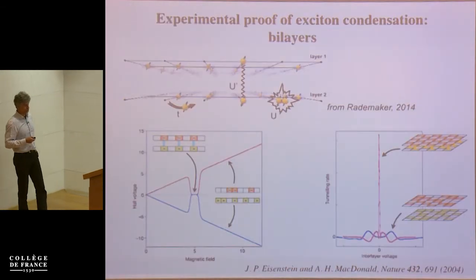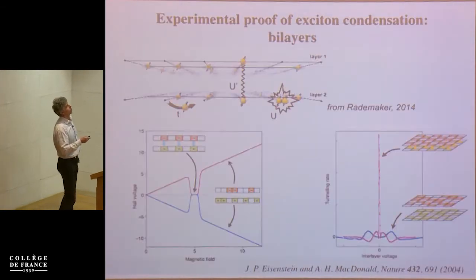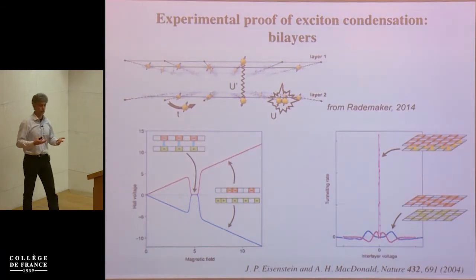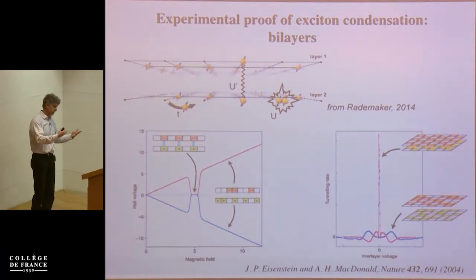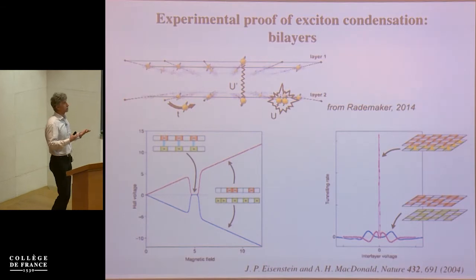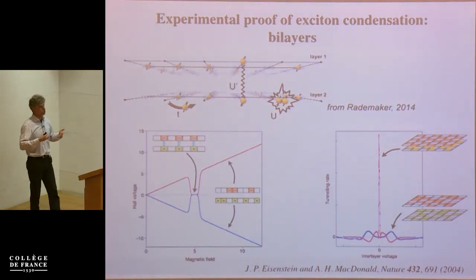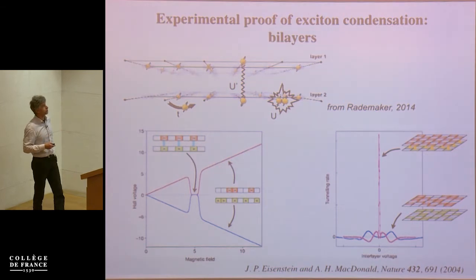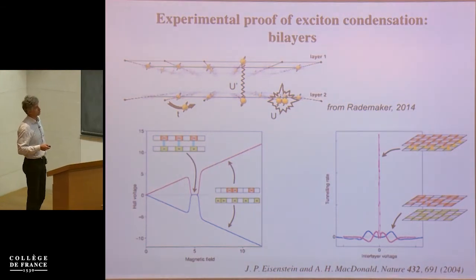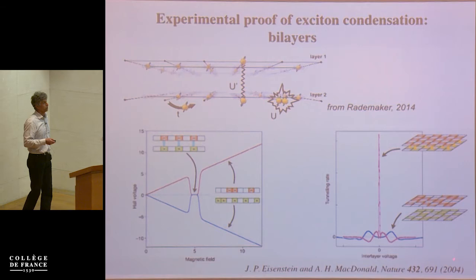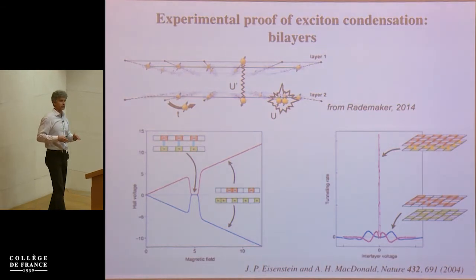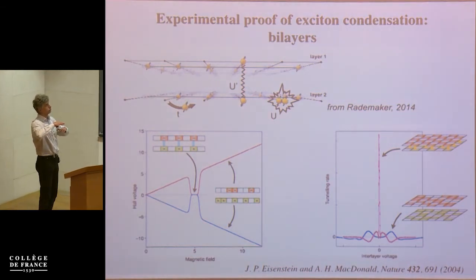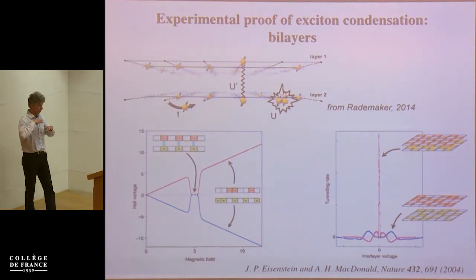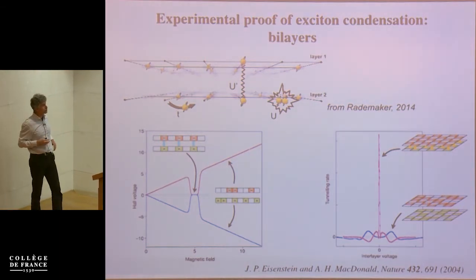So is there an experimental realization? Well, there are some experimental proposals in materials, but the experimental realization of this excitonic condensate so far was found in artificial heterostructures. So these are beautiful experiments by Eisenstein and MacDonald from 2004, where they built a bilayer of quantum wells. They had two-dimensional electron gases which were coupled to each other.